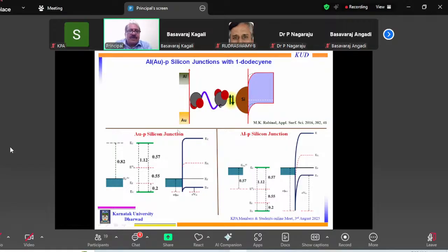So now if I try to draw the band diagram of p-type silicon and also take these metals, for example, this is for gold, this is for aluminum. Don't worry about this energy band diagram. What is the take-home message? I will just tell you that. What we have done is we have put the gold here with the work function, then the vacuum level, p-type silicon, and of course the molecular levels. And what I expect when I put gold on p-type silicon is that I should have a low barrier height.